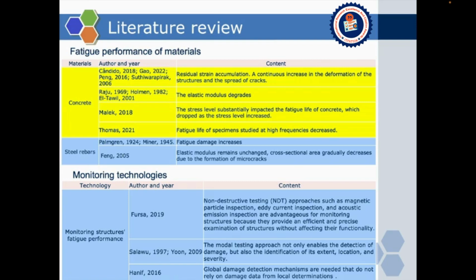Literature review. For this part, we focus on the fatigue performance of concrete and steel bars and the monitoring technologies. For concrete, fatigue loading can induce residual strain accumulation of concrete, resulting in a continuous increase in the deformation of the structure and the spread of cracks. It was found that the elastic modulus degrades as the number of cycles increases, and the stress level substantially impacts the fatigue life of concrete, which decreases as the stress level increases. At the same time, the fatigue life of the specimen tested at high frequency decreases.